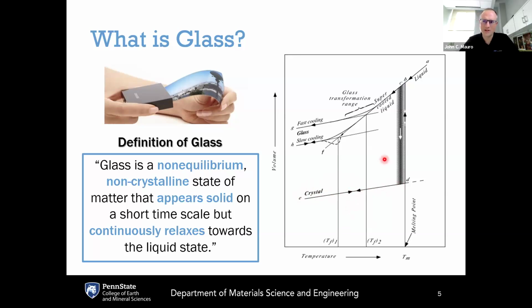But crystallization takes time. It takes time for the atoms in the disordered liquid structure to rearrange themselves into a crystalline configuration. For some liquids that have higher viscosities at their liquidus temperatures, it takes more time for the atoms to rearrange themselves into a crystalline configuration. And so for those systems, if you cool it fast enough through the shaded region so that the system doesn't have enough time to crystallize, then you get a phase which is called the supercooled liquid phase.